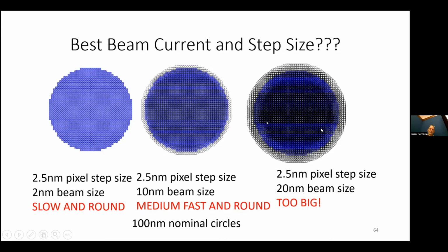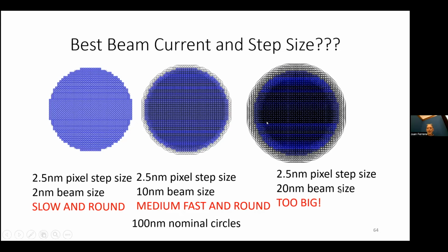Or we could say, man, we're going to do 20 nanometer beams. We're going to use huge beam current, and we're going to do this with tiny little step sizes. Now, the two problems here. One is that our feature is going to grow. You can see this here. We could fix that by biasing everything down and making it a bit smaller. But we're probably not going to have a clock speed that will allow us to give the dose we want, because we've got so much current in the beam and such a little pixel. We can't drive the beam from pixel to pixel fast enough to not overexpose.